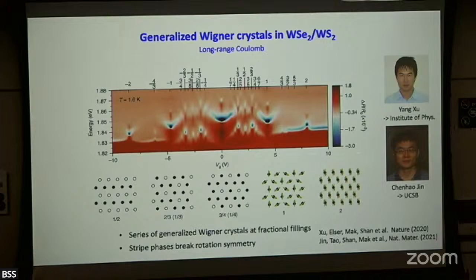The y-axis is the energy. What I'm looking at is the reflection contrast, as we talked about yesterday, at the frequency of the 2s exciton. And I already mentioned the 2s exciton is on the order of 5 to 6 nanometers, and my sensor is 1 or 2 nanometers away from my sample. So you see some enhancement, some very large signal, all those blue spots. It looks like a Christmas tree, but it contains a lot of information.